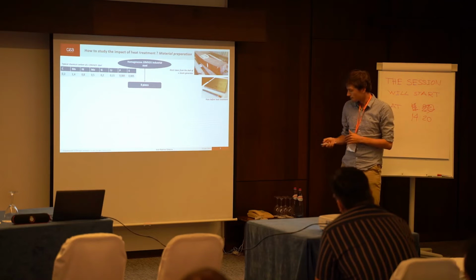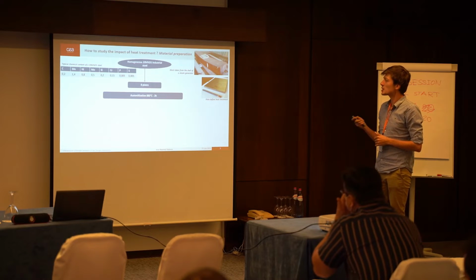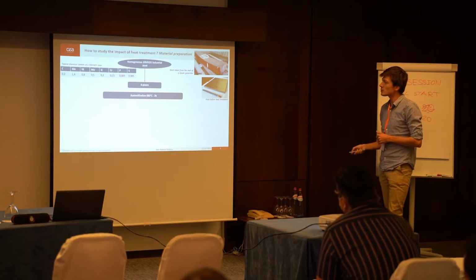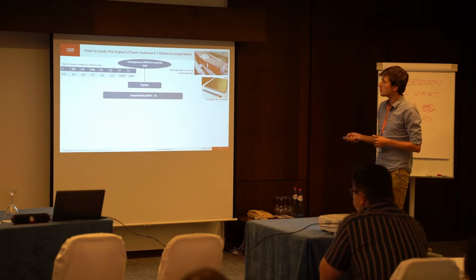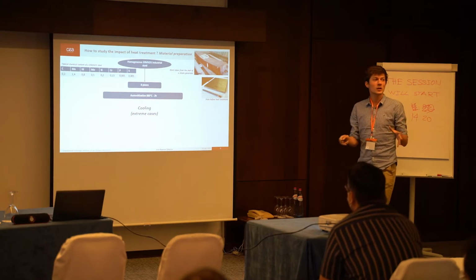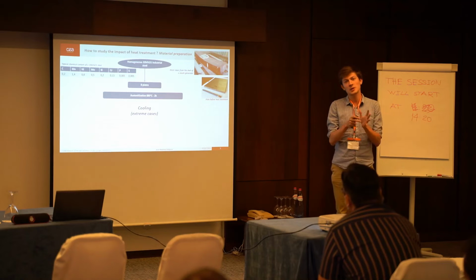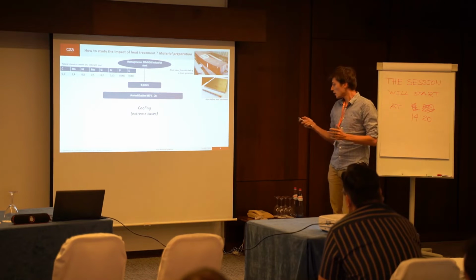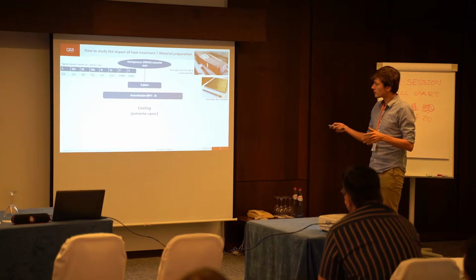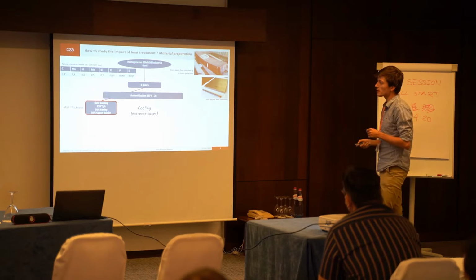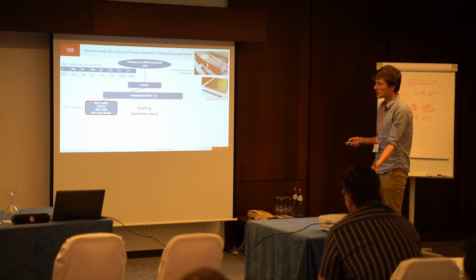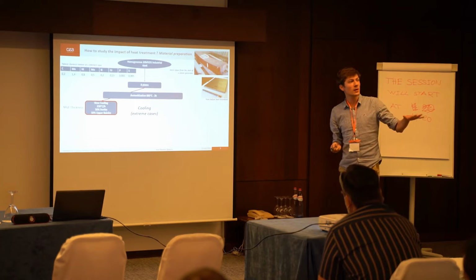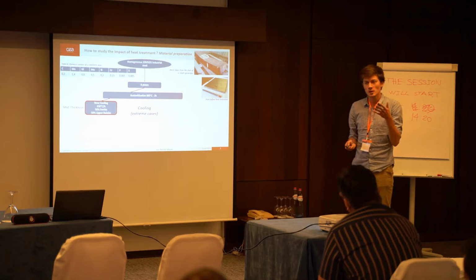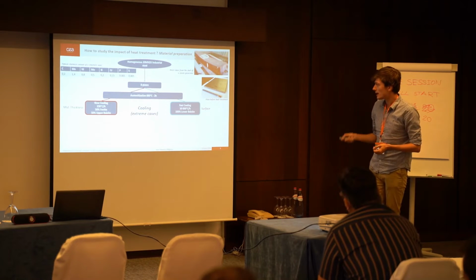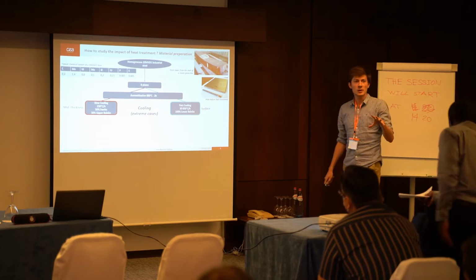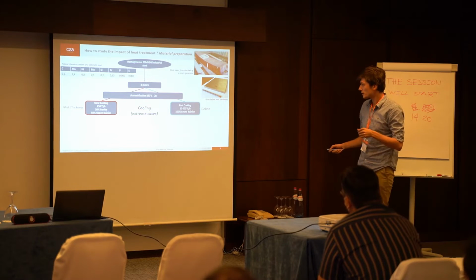different levels of thickness. So we start with an austenitisation at 808 degrees during 2 hours, followed by the cooling step. Here we consider the most extreme case of a component that is 700 mm thick. So we do 2 cases of cooling. One slow cooling at 150 degrees per hour, which is the cooling rate that you can have in the mid-thickness of the component, and fast cooling at 10,000 degrees per hour, which is the cooling rate that you find at the surface of the component.